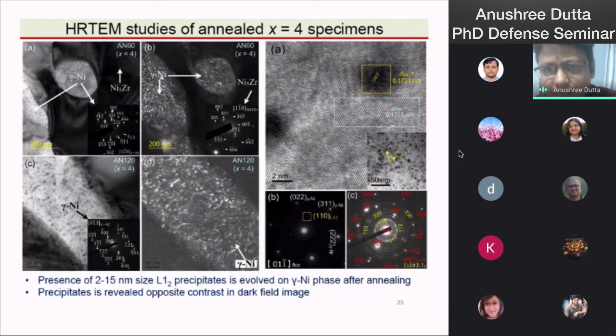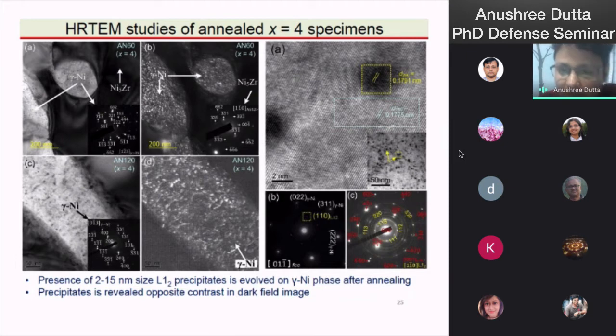Here, the high resolution microscopy image shows the lattice interplanar spacing, which has been estimated from this precipitate phase and the matrix phase. From there we estimated the lattice parameter of the precipitate phase and the matrix phase. And in the SAD pattern, we observed several L12 spots, such as 110, which evolved in the annealed SAD pattern, whereas in this SAD pattern we can observe the several L12 spots coming from the precipitate phase.